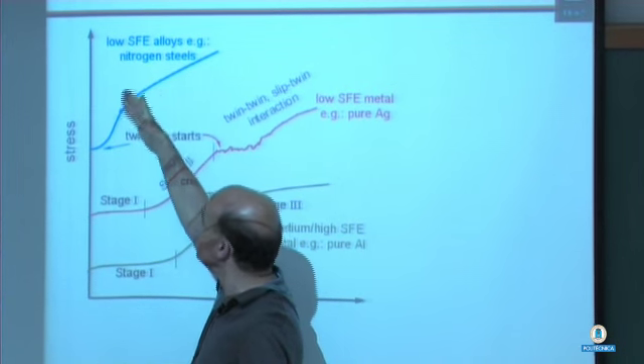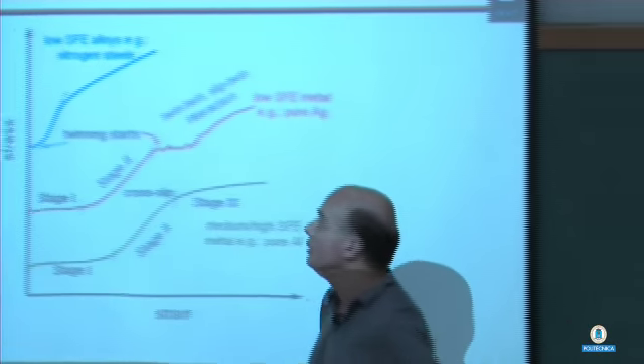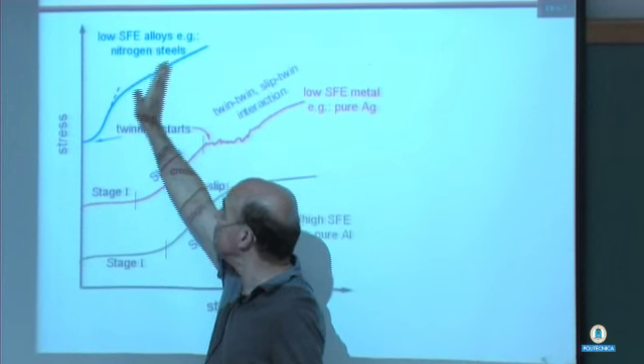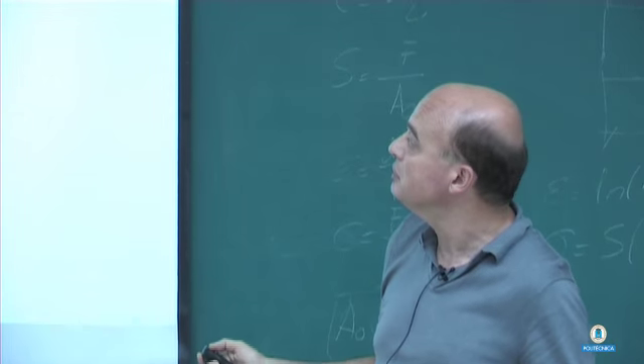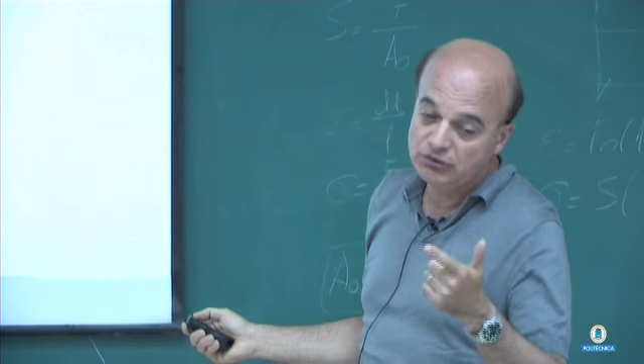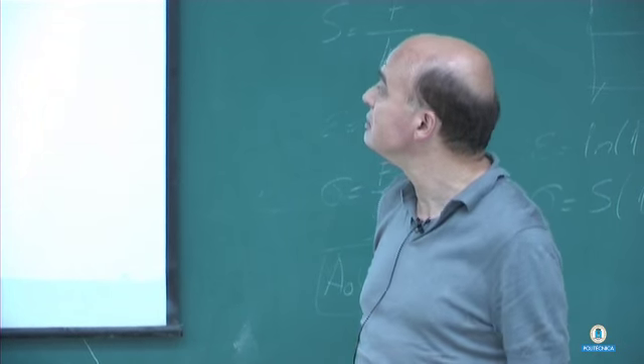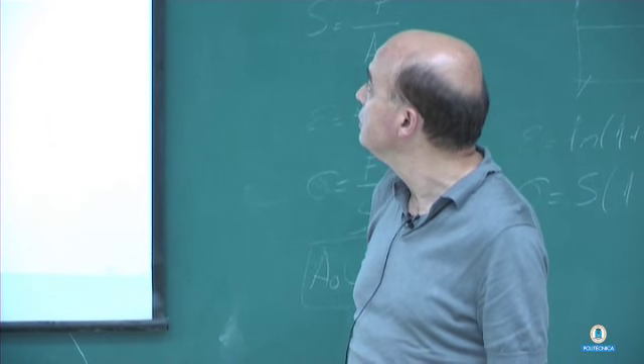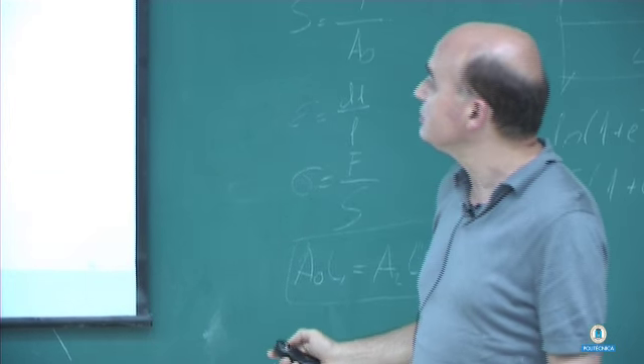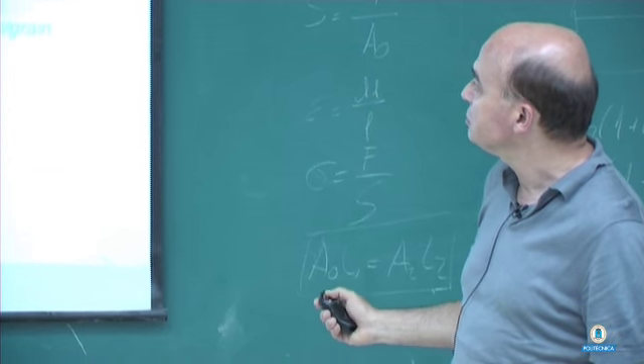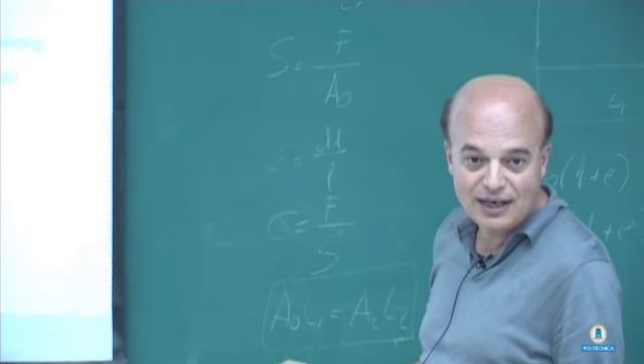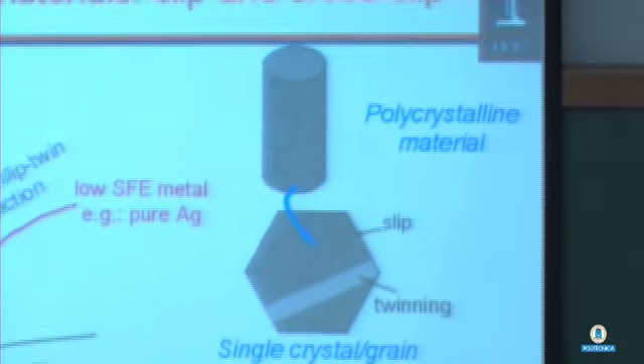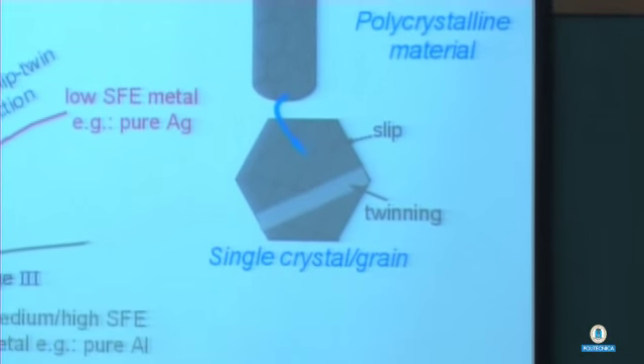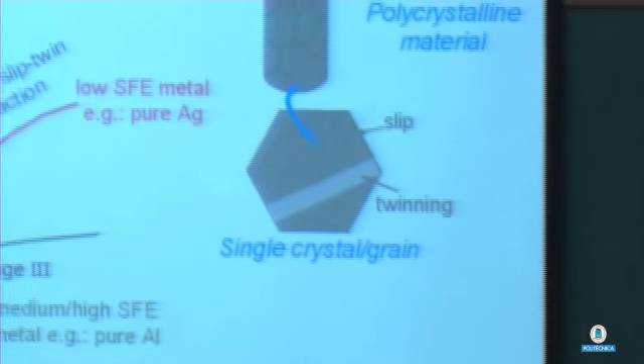But after a while, of course, you will get some linear hardening and then more or less parabolic hardening. So these are some nitrogen steels that are very important. Hadfield steels, some of the austenitic steels exhibit this behavior. Again, polycrystalline material has grains. The slip traces look like that. Twin has a volume associated with it, so you could measure the twin volume fraction or things like that.